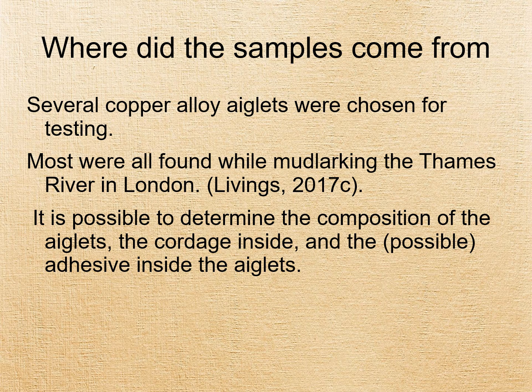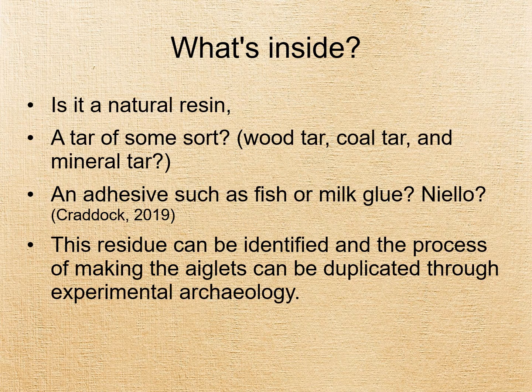It is possible to determine the composition of the aiglets, the cordage inside, and the possible adhesives used inside the aiglets. This still has to be researched. I used gum arabic, beeswax, bitumen, and pine pitch, with and without any added materials, as my adhesives. With the exception of gum arabic, all of these materials were eliminated as possible adhesives due to having to work quickly while they were hot.